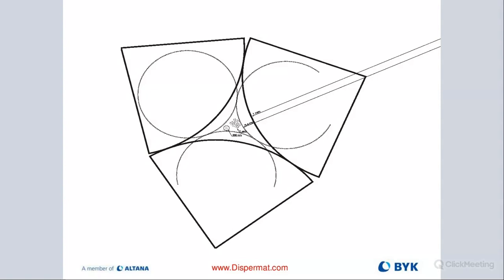We had one customer with three different products who came to us looking at a basket mill, and we were discussing the application. They told us that they use a 3-roll mill in production, and they sometimes need 2 days for a yellow to get down to the correct particle size. They didn't really know what to expect when they came to our lab. Then we took the TML1, which is our basket mill, and we were milling it, and we were done in 1 hour and 45 minutes. So that's just an example of how efficiently we can mill when we optimize all the right parameters.